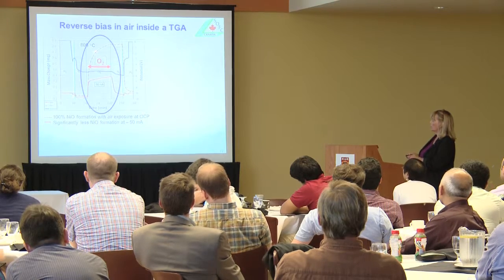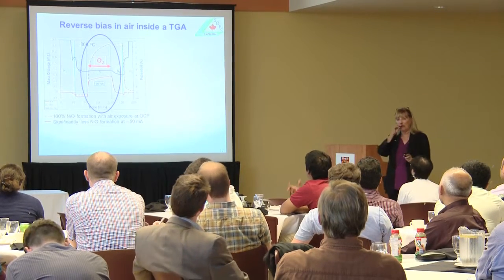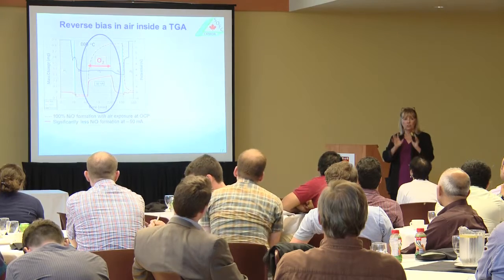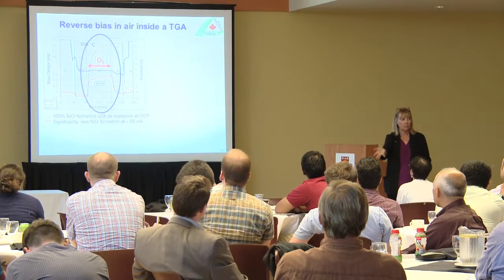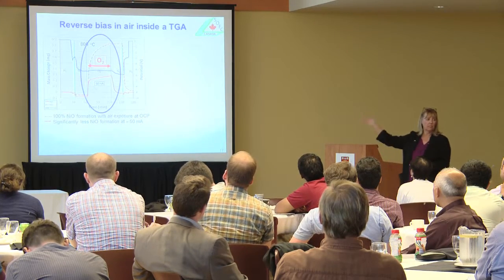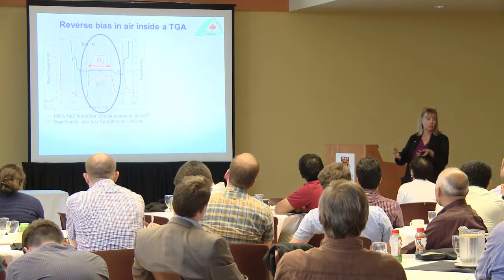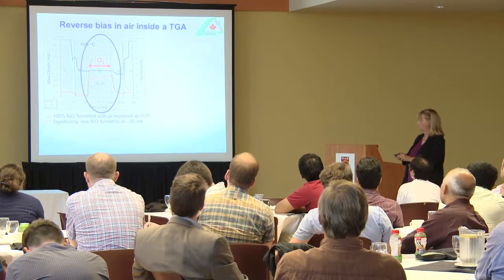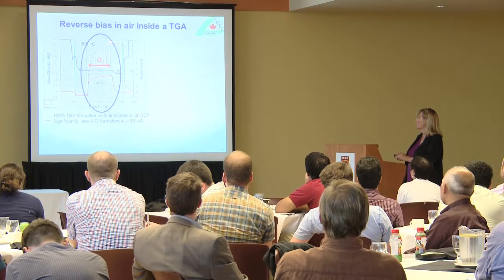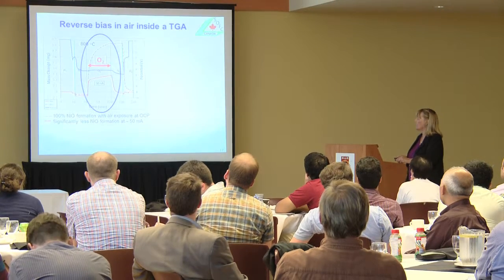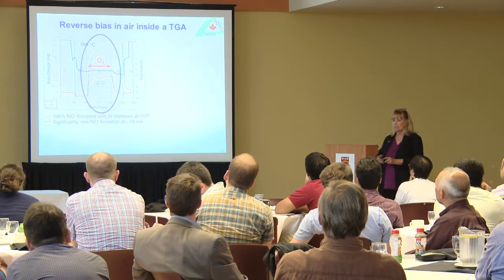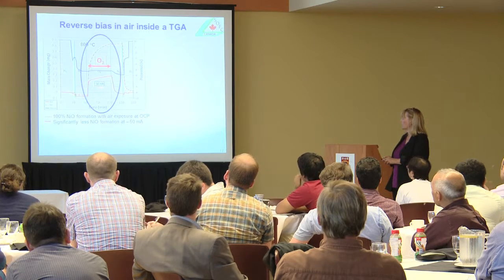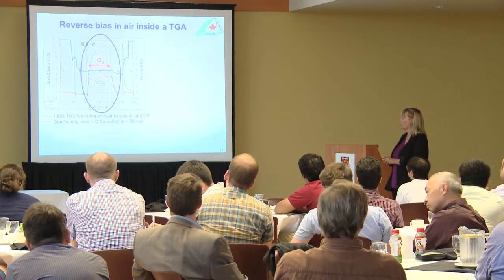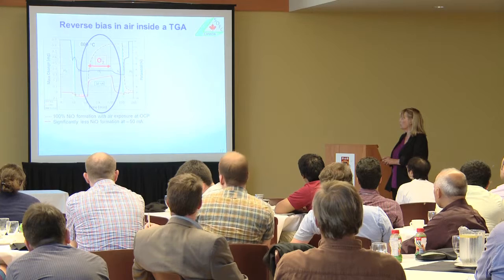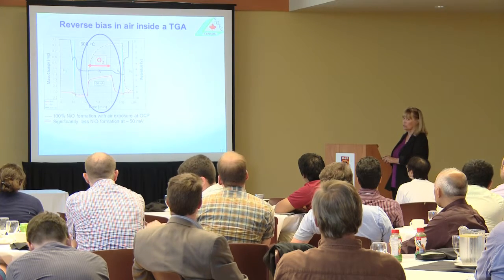Starting with the dashy line, the dashy line is what you see when you're just at open circuit. You're just letting nickel see oxygen, and the mass gain is equivalent to full oxidation of all the nickel that's there. So that is 100% oxidized, you can see, you can reduce it. Then, I'm just showing one of the results. This is the case with a negative current applied during the same experiment. Of course, you can see that the mass gain is much less.